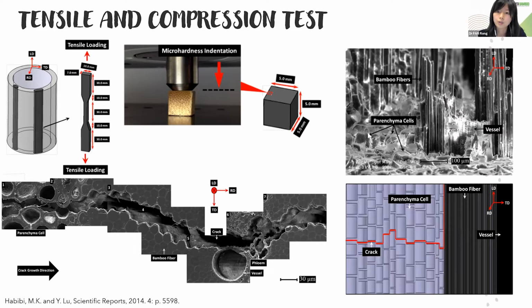And this is a picture to show the fracture surface of the tensile bamboo. We can see that the bamboo fibers were pulled out. This is the most prominent feature in the tensile fracture surface, which could be simply created to exhibit crack growth along the fibrous interfacial areas in both the radial directions and the longitudinal directions.